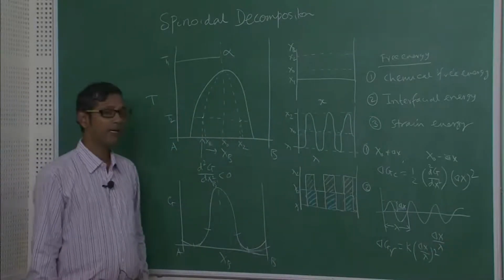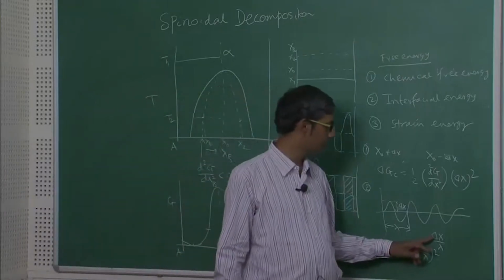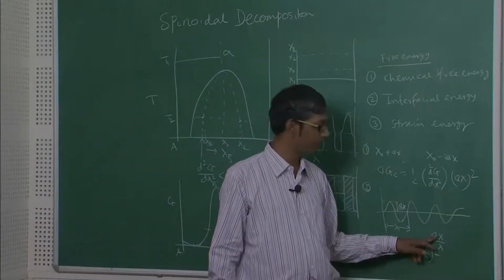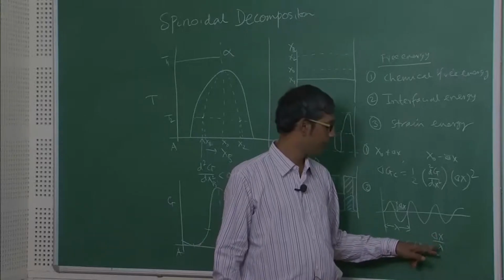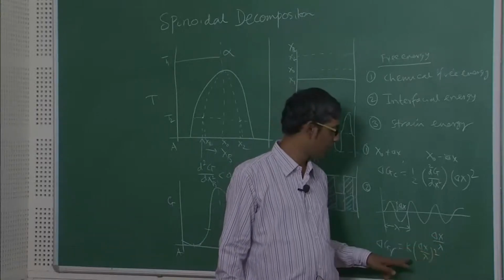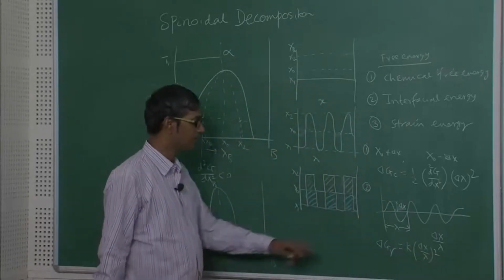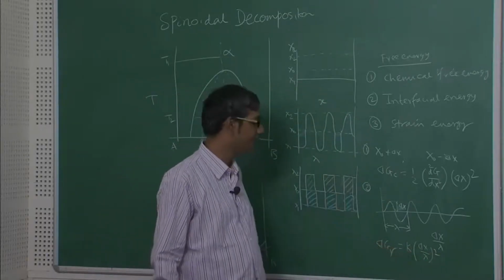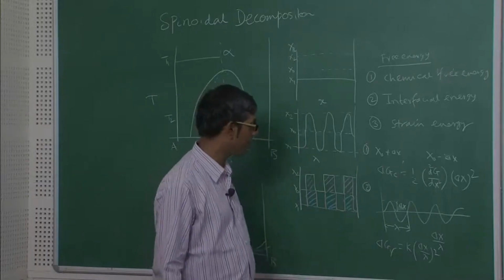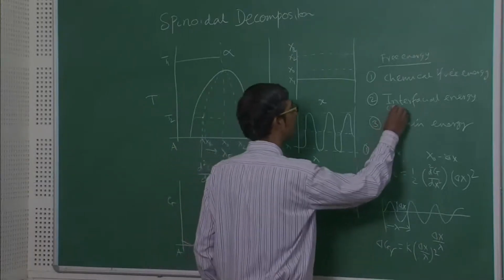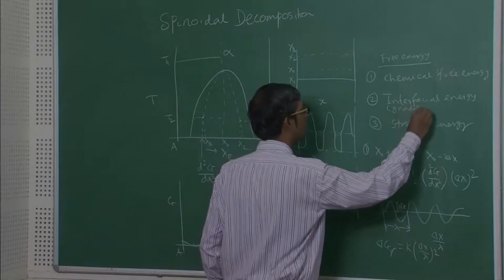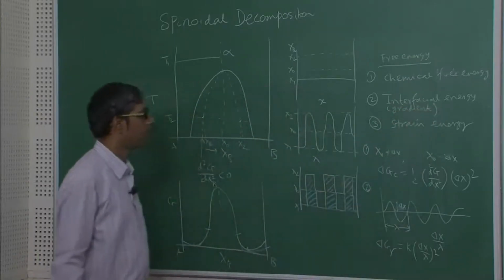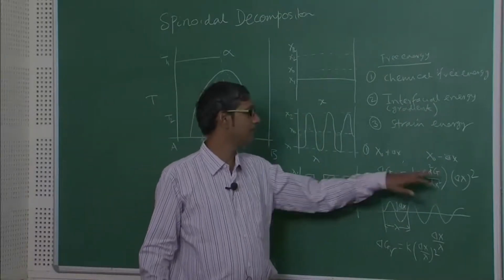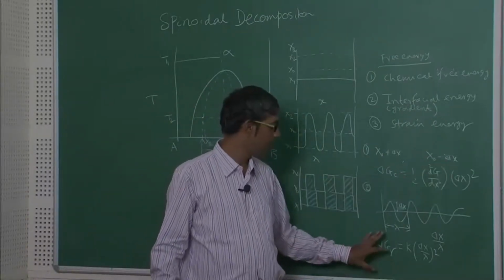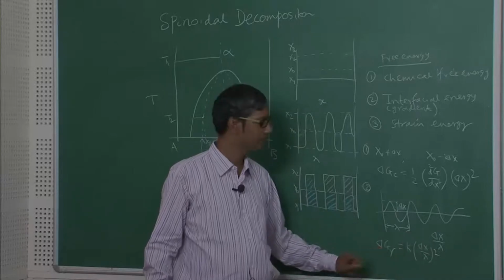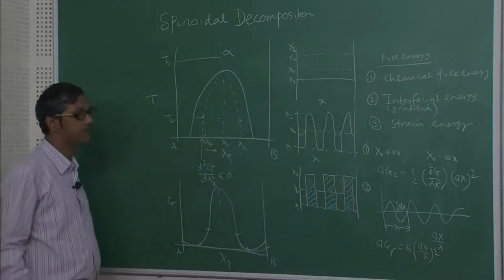Okay. Why? That is because this is composition, that means atom percent, and this is the distance lambda. So, it is atom percent by distance. In order to give it units of energy, we have to multiply with the constant k. K is basically the gradient energy constant, okay. Therefore, this energy is also known as gradient energy, because of the compositional gradient present in the system, right. So, we have seen that the chemical free energy is like that, and the compositional gradient leading to interfacial energy is like this.